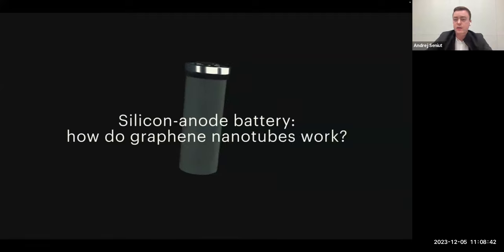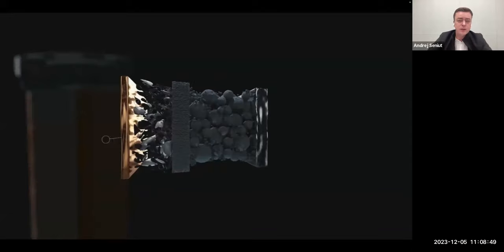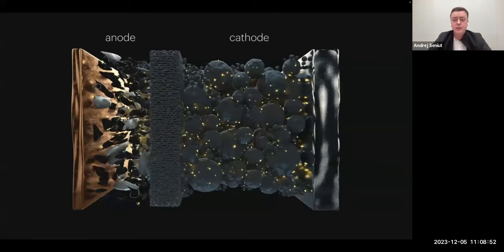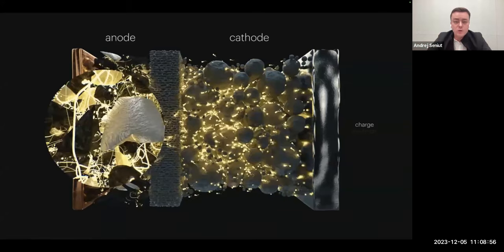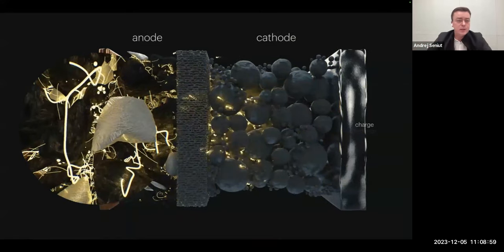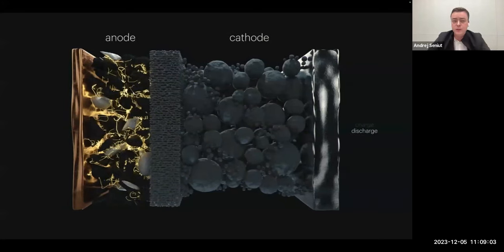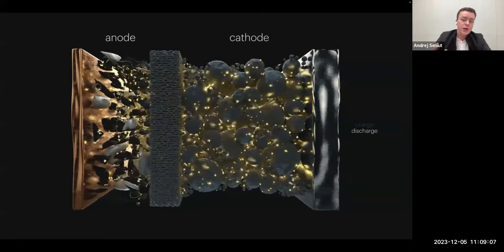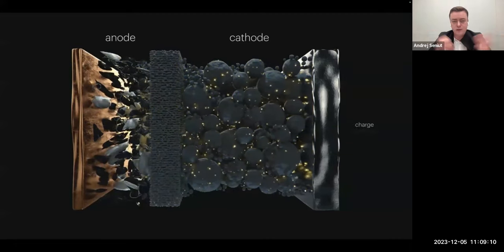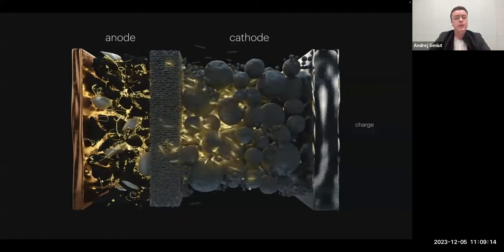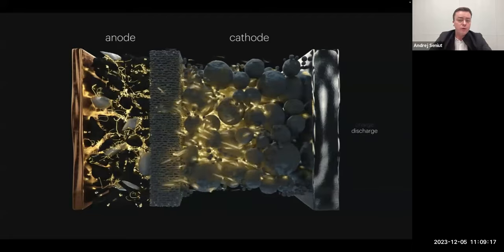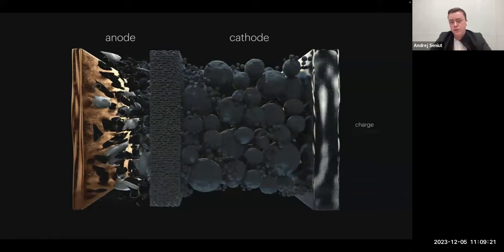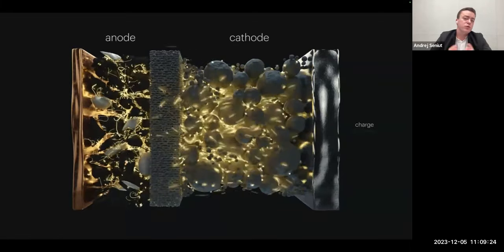To start with, I'll show you a very brief illustrative video about how single carbon nanotubes work inside a silicon anode battery. The mechanism is really simple. Now you can see a crosscut of the cylindrical battery. To the left is the anode side. To the right is the cathode. And these yellow dots are lithium ions. These black particles are the particles of silicon anode material. And as you can see, during the charging process, silicon anode particles enlarge. During discharging, they contract. And over this course of expansion and contraction, there is a loss of electrical contact between silicon anode particles, which leads to rapid battery degradation.